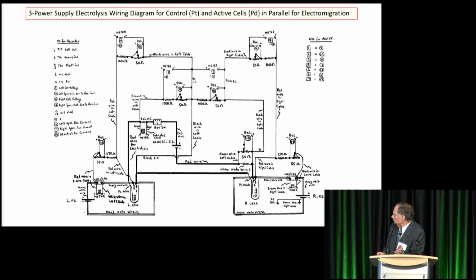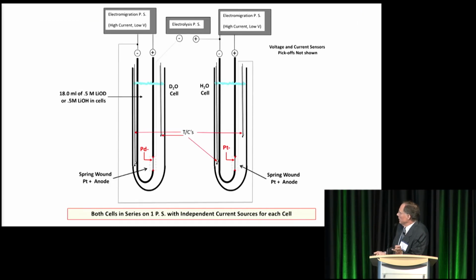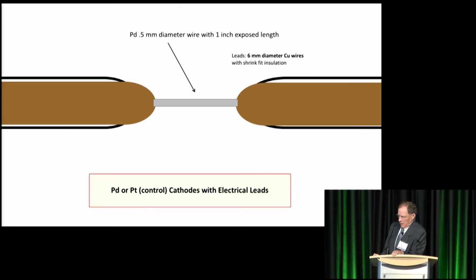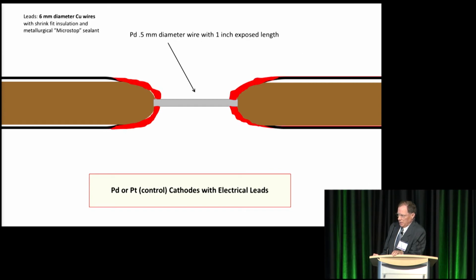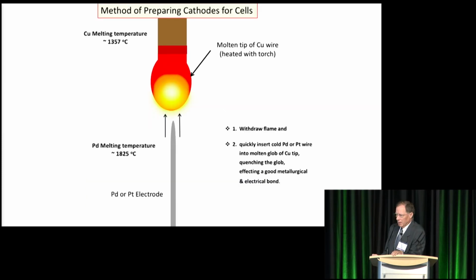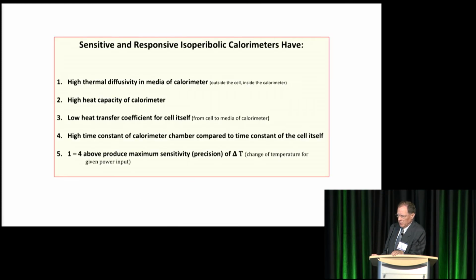This is the diagram, shown here with twin cells, one heavy, one light, run in series, with 3 power sources: one to run the electrolysis, and one dedicated to each of the cells to run the electromigration. The specimens were prepared by putting them into heat shrink insulation, using microstop to seal them, and then the specimen was inserted into molten copper, prepared that way.